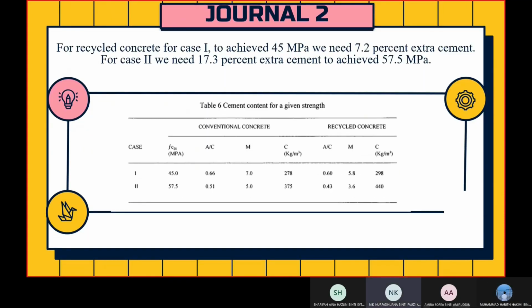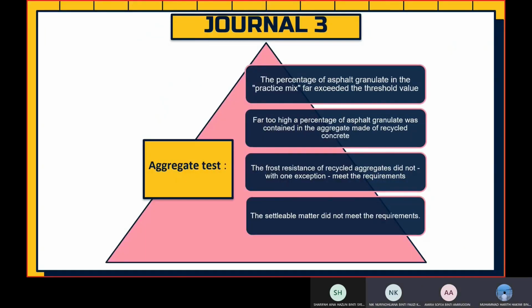This Table 6 is the cement content for a given strength. For recycled concrete for case 1, to achieve 45 MPa, we need 7.2% extra cement. For case 2, we need 17.3% extra cement to achieve 57.5 MPa. Now, for the findings of the third journal, first is the aggregate test.